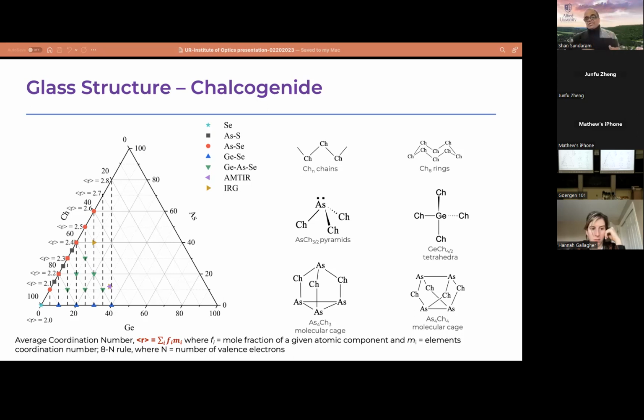For the chalcogenide family, one of the interesting things is they are predominantly covalently bonded glasses. Because of the various chemistry and the layered structure of the glass, we see a much more interesting range of structural units inside these glasses, anywhere from chains and pyramids to molecular cages of various combinations of these chalcogenide elements. This is a very well-known family of glasses for various applications. We use this value R, which we call the average coordination number, because there are various structural units mixed in this glass structure.